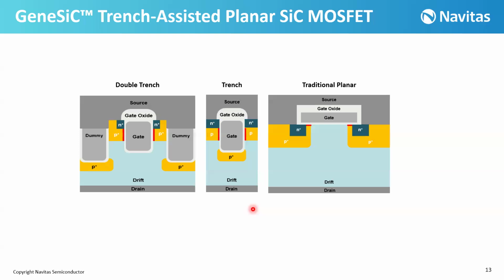In the double trench, if you look at the middle part here, it's exactly the same as this traditional trench. We have the N+ source, P-well here, we have both channels, and then we have the gate. But instead of having the ion implantation under the gate, normally we can make two dummy trenches here, and then have this P+ implantation under these dummies. And by this P+ implantation, we can actually provide a shielding under the gate oxide. This is one way.